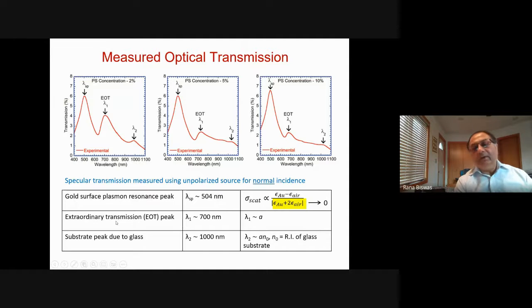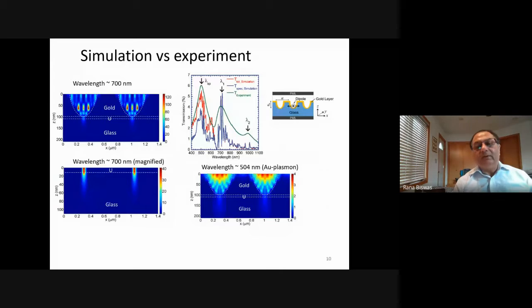So in summary, we are seeing this extraordinary optical transmission, even though we have a continuous metal film. And we did no etching. So this was our big finding when we did these experiments. So then we set out to understand what is actually happening by doing simulations. And here we do scattering matrix simulations, calculating the transmission of light through this nanocup in a gold coated substrate.